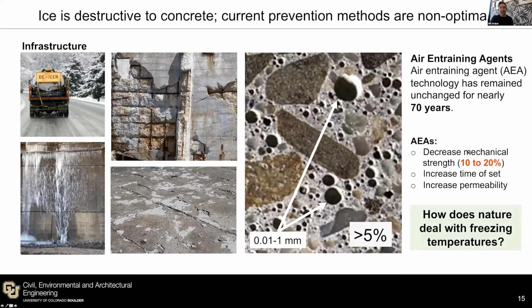Number one is that air cannot carry load, so it inherently weakens the concrete. Number two, which can be of concern for departments of transportation, is that when you put in the admixtures to make the air bubbles, it can increase the time of set of the concrete and delay construction. And the biggest one, number three here, is that it increases the permeability of concrete.